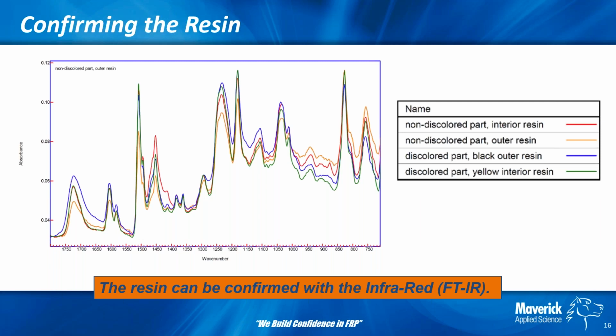And if we knew what it was before, we could also go to the resin company and ask for this data and overlay it, and you could compare. In our experience, it would tell you better than about 95 to 97% whether it's agreeable or not. If it wasn't, you would see an odd spike in the middle of this that wouldn't match up. But in most cases, we find that it overlays pretty much like what you see here. So we feel that's pretty good confirmation of the resin when we see that.